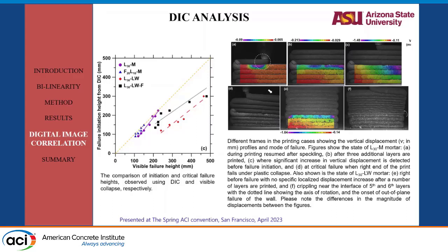So just for the view of it, the top 3 figures show a plastic failure response. It was captured for a plastic failure type. The initial picture shows the vertical strain being very high on the lower filament because of the print head nozzle. But once enough layers are built, we can't see that strain concentration on those layers.